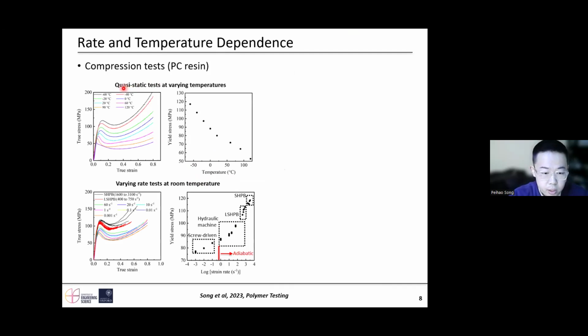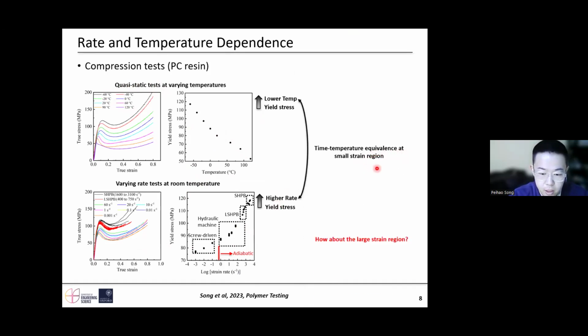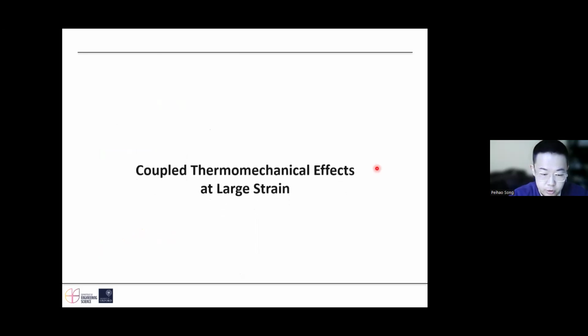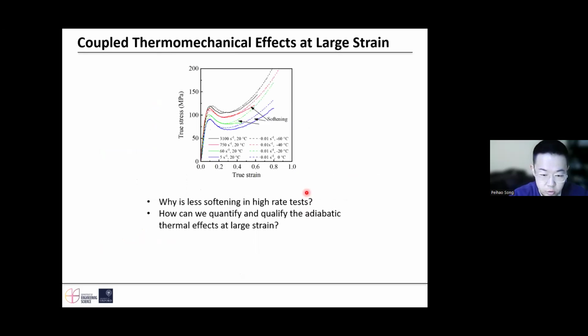So here is the quasi-static test at varying temperatures from -60 to 120. If we decrease the temperature, we can see higher yield stress. And here is the rate-dependent test. If we increase the rate, we can get higher yield stress, which we call time temperature equivalence at small strain region. So how about the large strain region? It brings me to the next work, coupled thermomechanical effects at large strain.